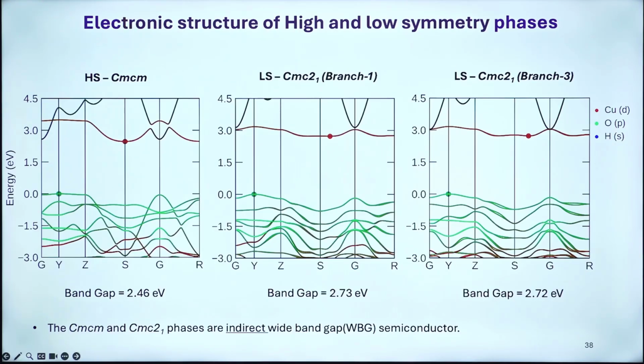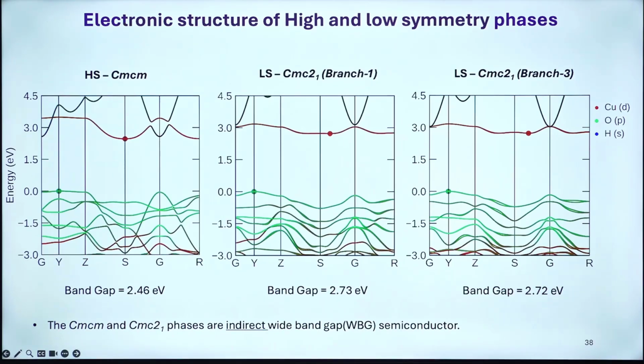We have taken care of the correlation effects, because the band gap is always a problem in density functional theory. All of these have around 2.5 to 2.7 eV band gap. So it's an indirect wide band gap semiconductor.